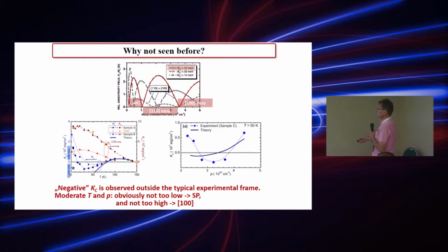If anyone was performing measurements at very, very low temperatures, then of course this superparamagnetic component was giving this concave curvature, obscuring the change of the cubic anisotropy to negative values. Very few people were interested in this middle temperature or middle hole concentration regime where the negative values of cubic anisotropy were possible to see.